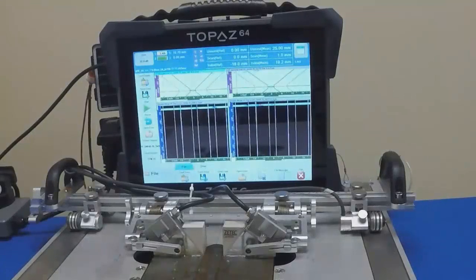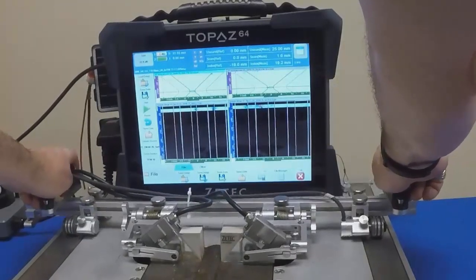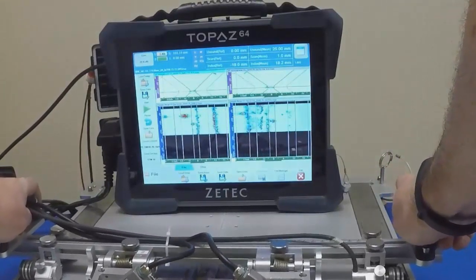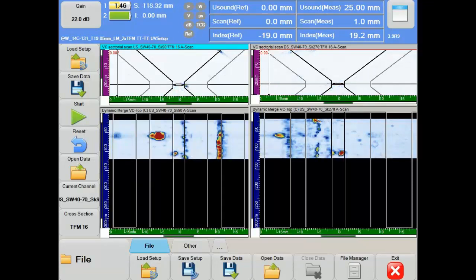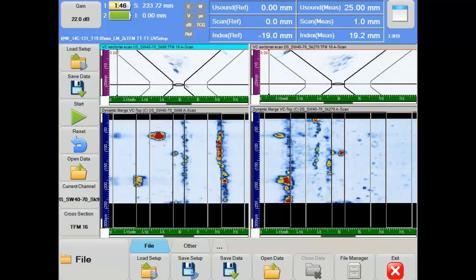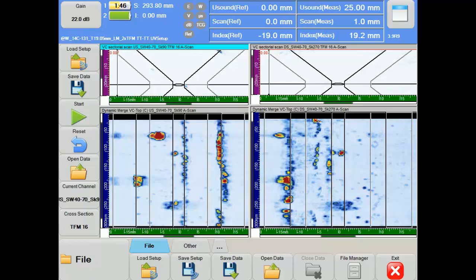The Zetec weld crawler is used to carry the probes for this one-line scanning sequence. In this case study, only the live TFM frames are recorded — no raw FMC data will be stored. This allows for a scanning speed around 25 mm per second while recording frames every mm. This is only slightly slower compared to two-sided standard phased array with similar inspection parameters. The live TFM data file size for this type of weld is around 350 MB for a weld length of 1 m, roughly double the size of standard phased array.